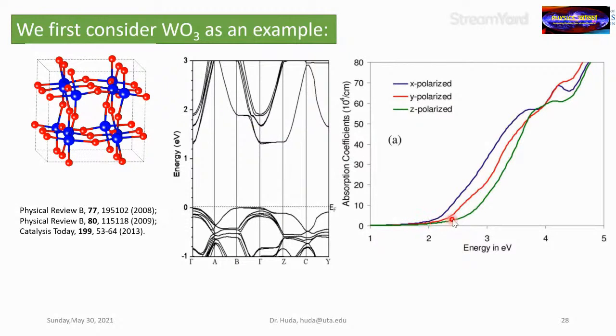As you can see, the electron absorption probability, or the absorption coefficient, doesn't increase much before somewhere like 2.3 or 2.4 electron volt. That means we are blocking all the red light and some part of the green light as well. Where we want most solar light absorption is around this region, and around this region the absorption probability is very low. That means with this natural gap, it cannot be used efficiently for solar light absorption, and hence for either photovoltaic or photoelectrolysis materials. We need to change this feature. We need to enhance the absorption around this region.